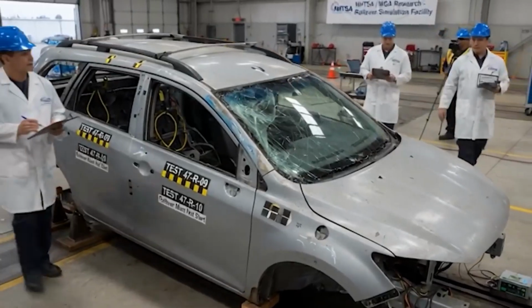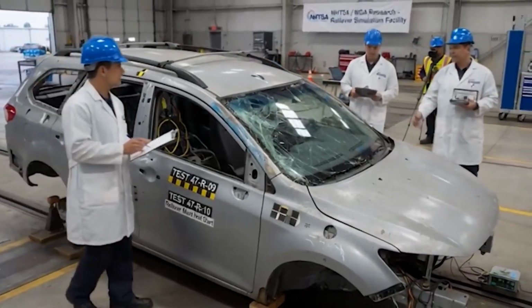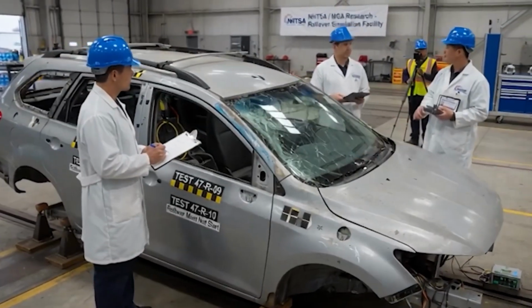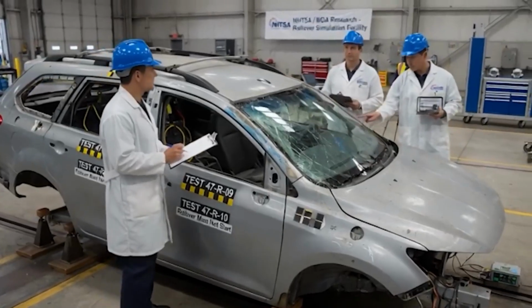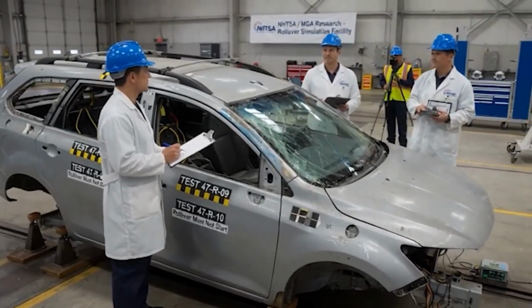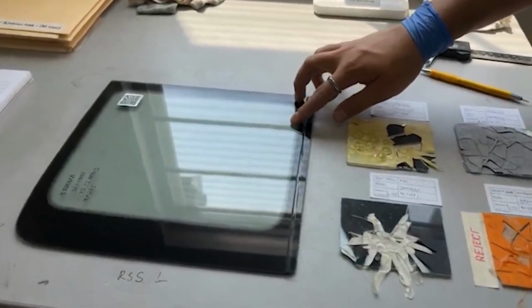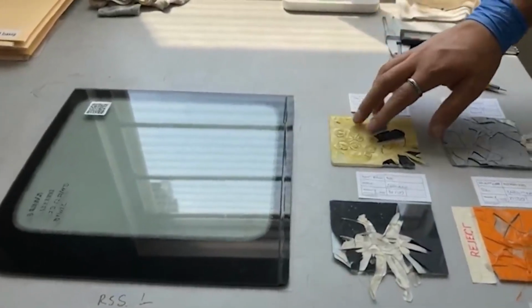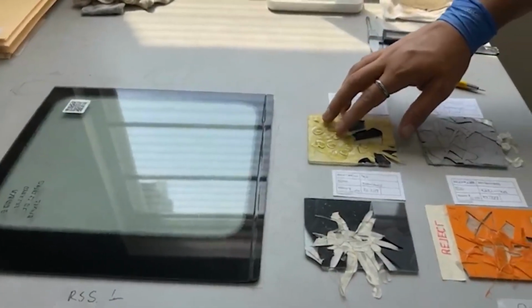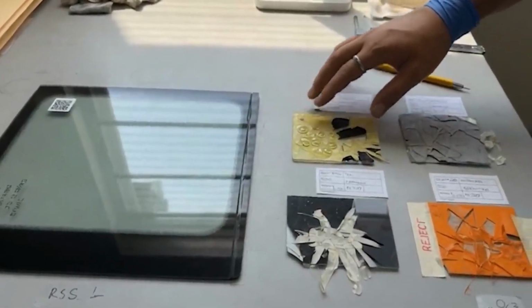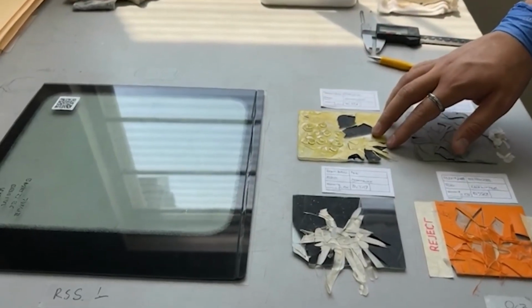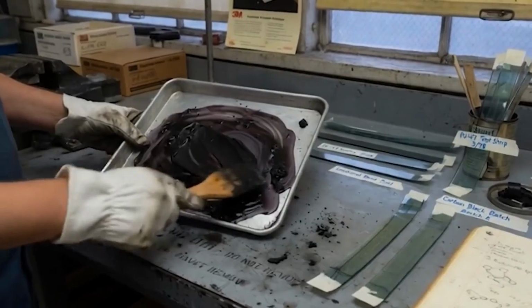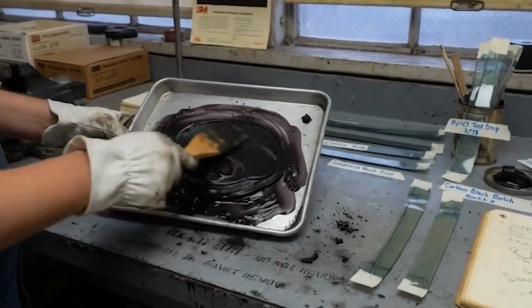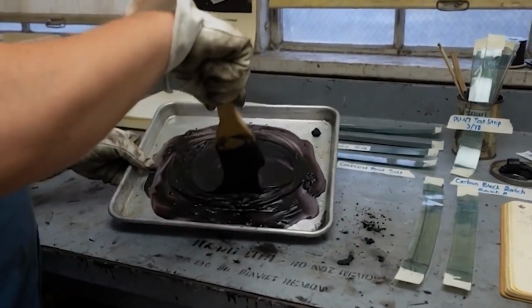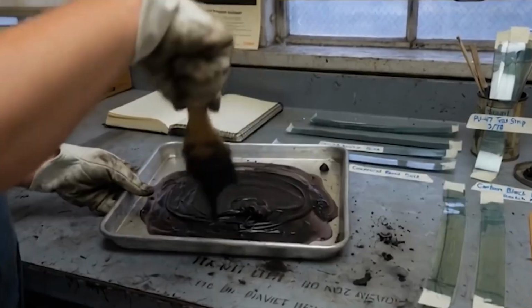But a new problem quickly emerged. The powerful adhesive holding the glass in place had an unexpected weakness. Sunlight. Polyurethane adhesive doesn't like ultraviolet radiation. Over time, sunlight passing through the glass slowly breaks down the chemical structure of the adhesive. The glue becomes brittle. It develops microscopic cracks. Eventually, its bonding strength begins to deteriorate. In extreme cases, the windshield could lose part of its structural integrity.